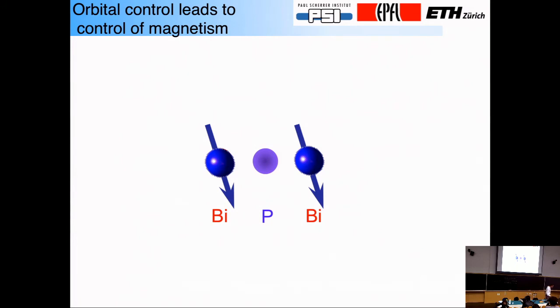Another thing that has really motivated us from the beginning of this project is the possibility, with optical control of the orbitals, that you can control magnetism. And it's quite simple to see how that works, and I've just constructed this video to show that. Let's say I have two relatively deep impurities, bismuth impurities, separated by a phosphorus impurity. And so I have my long-lived spin states associated with each of the bismuth. And if the phosphorus is sitting in the 1s state, there's not much overlap with these neighbors.